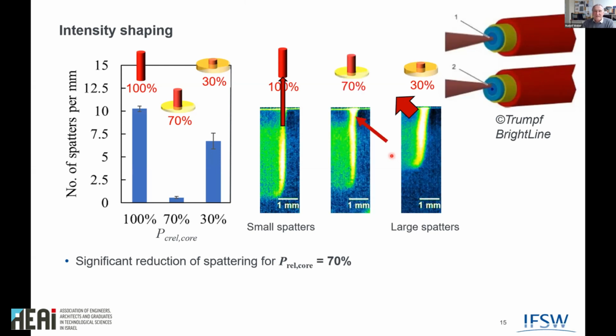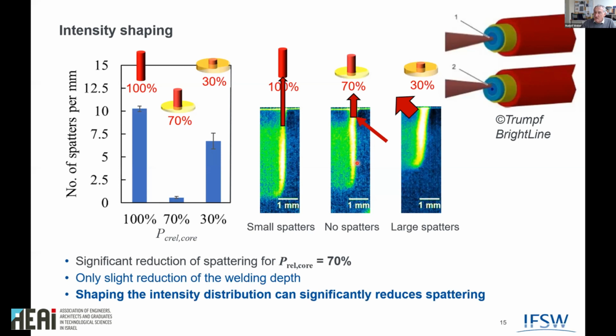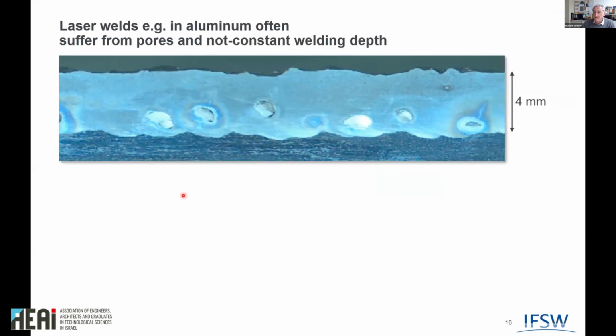So there is of course a stage in between where, with this small ring, we slightly open the capillary, which means the flow velocity dramatically drops, and the number of small fast spatters is decreased, and the large ones did not come yet because the capillary is still narrow and deep. Very simple, very effective means to reduce spattering.